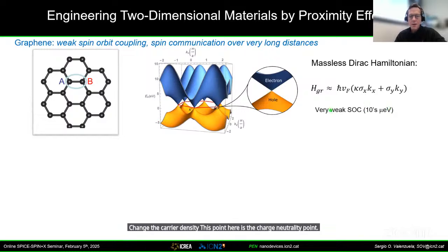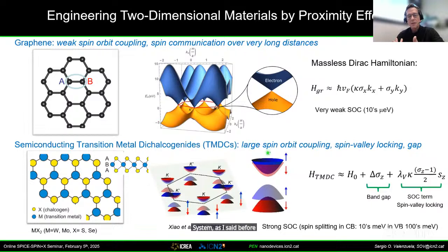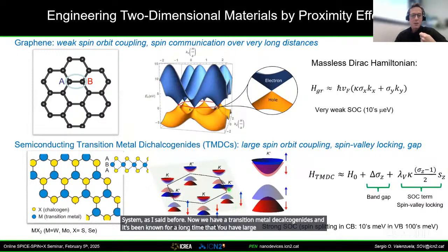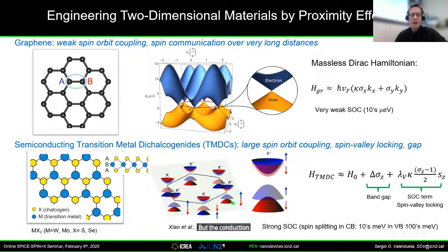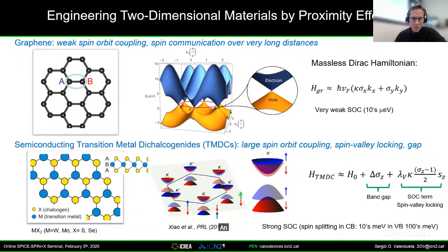And in graphene, the spin orbit coupling is very weak, and so you can use it as a spin communication system, as I said before. Now we have the transition metal dichalcogenides, and it's been known for a long time that you have large spin orbit coupling in the system. You also have states in K and K prime, but the conduction and valence bands are split. The splitting here is of the order of hundreds of millielectron volts. The splitting here is still of the order of tens of millielectron volts, much larger than you have in graphene. And there is an alternating orientation of the spin, up to down, from one valley to the other. And this is simply a consequence of conserving time reversal symmetry.